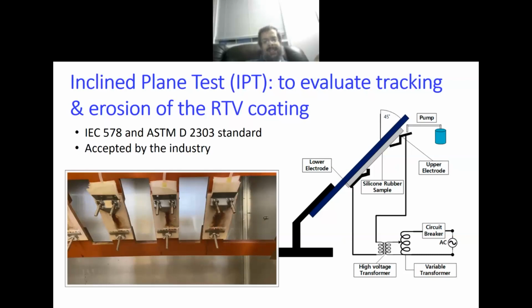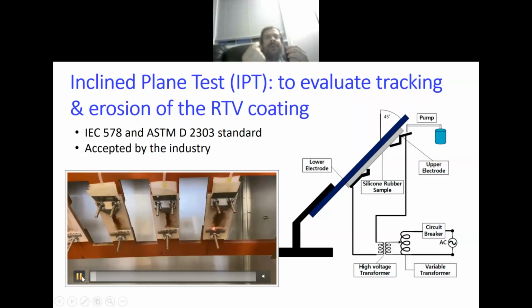So basically, what is this test? You have the samples. These white materials are the samples, and this is a sample of the silicone rubber. We have it at 45 degrees. Then we use peristaltic pumps to gradually pollute or wet the surface with a conductive material. You can see the peristaltic pumps from the top of the samples, and these are some papers. They will be wetted so that you will have a smooth flow of the water, not a pulsating flow.